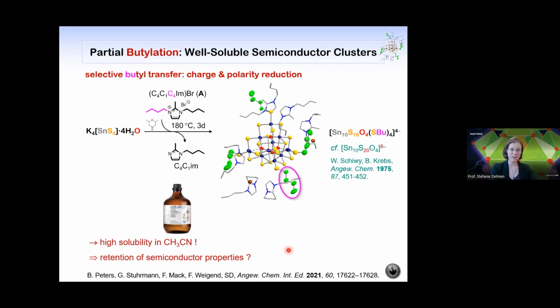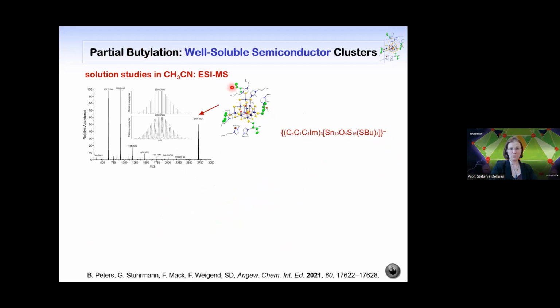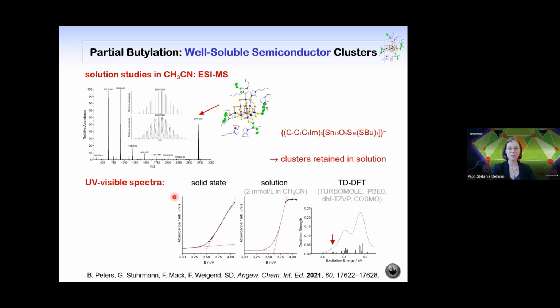And we can show that these dissolved clusters are still intact, and we can look at the semiconductor properties of them. First of all, we had to prove that they are intact, and we can show it with mass spectrometry and NMR spectroscopy that they are retained in solution. And UV-visible spectra tell us that the solid state spectra and the solution spectra are nearly the same. You will find roughly the same absorption properties and band gaps. So the semiconductor-like optical gap persists, and it can also be calculated. So we can take these clusters and just alkylate them a little bit to make them soluble, but keep their properties as semiconductors, which is maybe interesting for photocatalytic applications in the future.